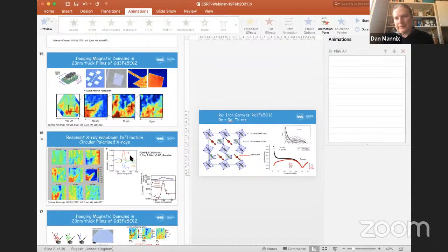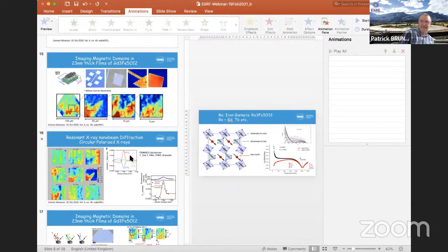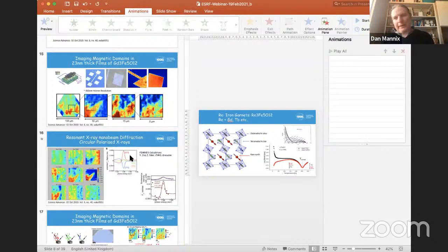Yeah. But for the inelastic, it's hard because of the extra background from electron-hole excitations. But for the diffraction, you say you could do it. Yes, depending on what the metal was. I mean, if you had to work in a hard X-ray regime and work on something like iron, I think that would be very difficult because the magnetic scattering is very small in the hard X-ray regime for iron, and if you had to do diffraction as well, that wouldn't work. I was actually hoping iridium manganese.